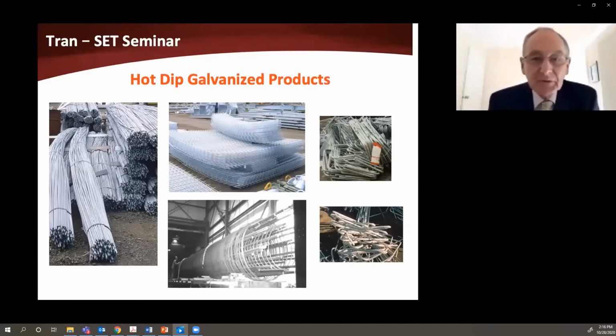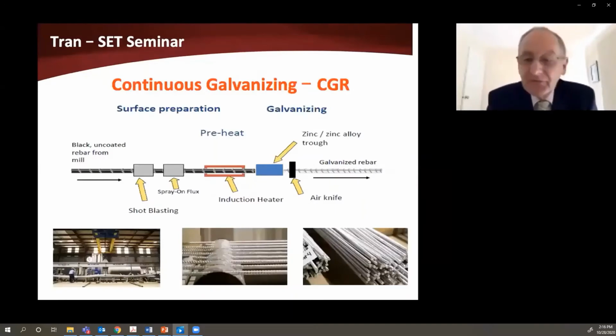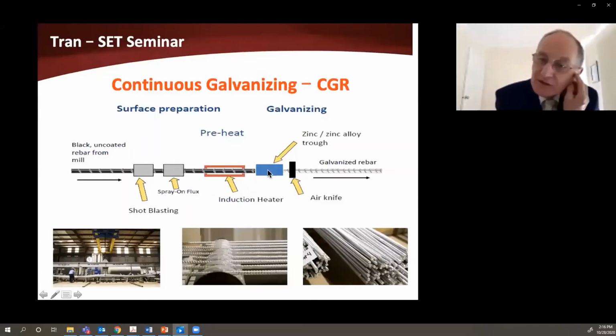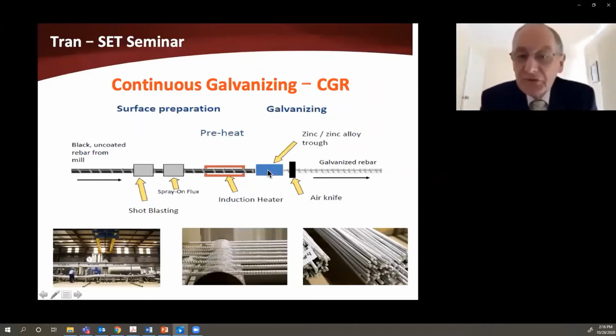And again, the size of these products is determined by the size of the bath that you have available. With continuous galvanizing, as I mentioned, this has come from developments or long-term use in the oil and gas and pipe and tube industry. Straight lengths of bar are put through a facility where they are blast cleaned, a flux is sprayed on, they're heated, and it goes through a zinc trough, and the steel is only in that zinc trough for literally a few seconds. And then an air knife cuts the residual fresh zinc off the surface, and the product comes out the other end.